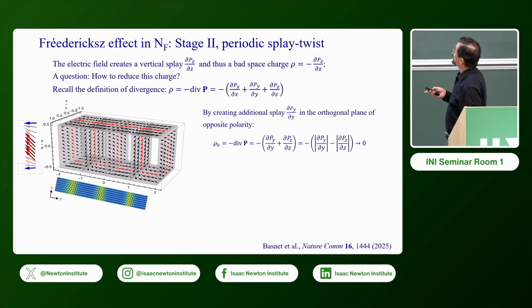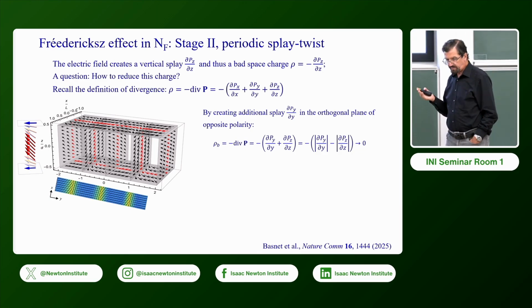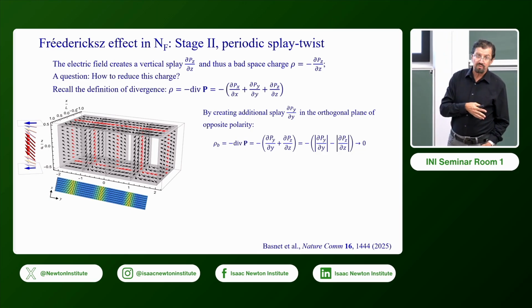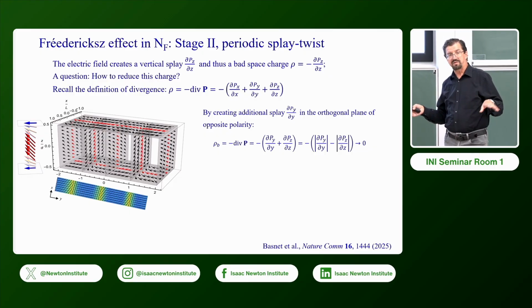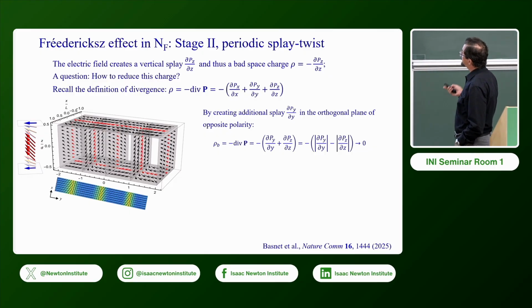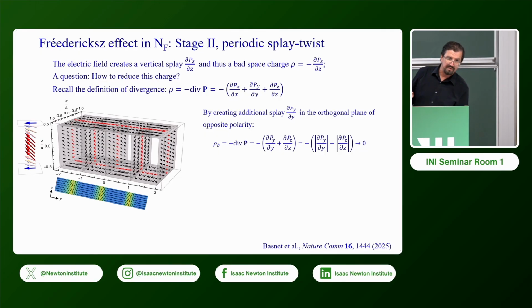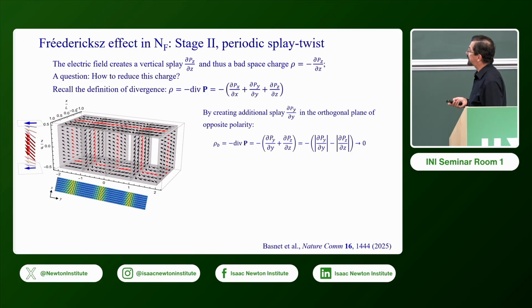We simply recall the elementary math, the definition of divergence P. If you have a non-zero part here, then you can reduce it by producing a non-zero variation in the orthogonal direction, provided that the signs of those two derivatives are different. Then the electric field induced space charge would be reduced by additional deformation in the plane of the field. So it's a very nice, purely geometrical solution to the electrostatic problem.